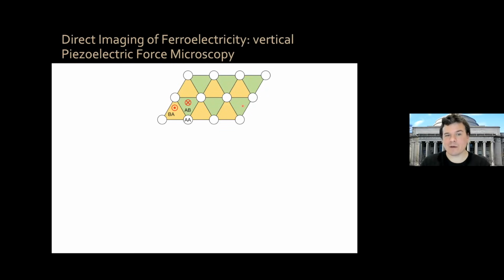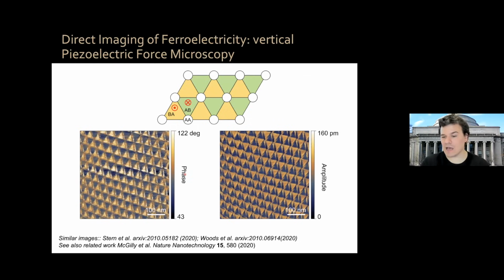Now, can we do direct imaging of this ferroelectricity? We can, okay? If you take one of these twisted samples and you look with vertical piezoelectric force microscopy, okay? These are images, phase and amplitude, directly imaging the electric field from the electric dipole moments of this ferroelectric behavior. And you can see the AB and BA domains in this beautiful honeycomb pattern, okay? This is something that, again, was also done by two other groups independently.